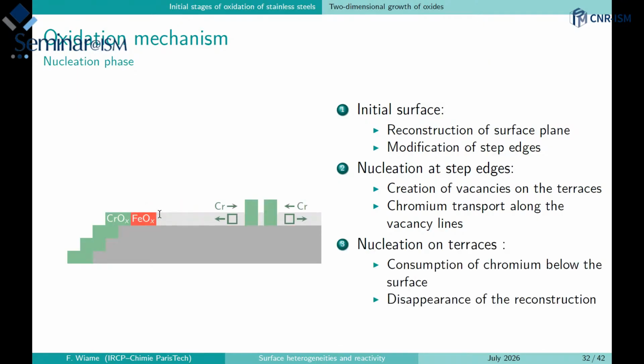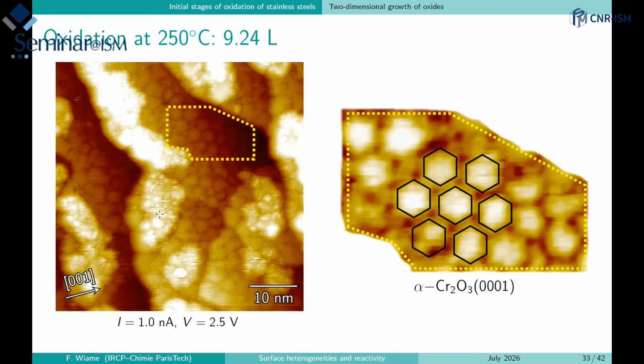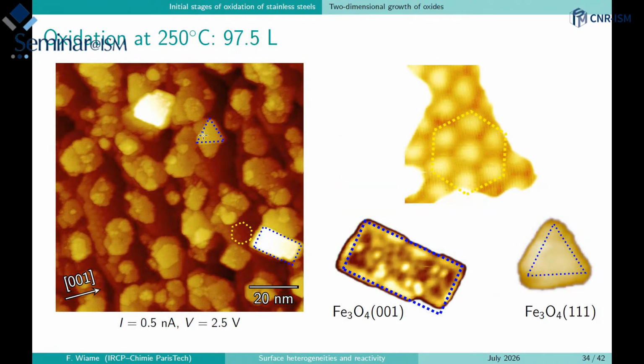And then we have the formation of the nucleation of chromium oxide on the terraces. So that means that we already have consumed all the chromium from the top surface, and also the appearance of some iron oxide. If we continue the exposure, then we have another structure, a hexagonal structure of chromium oxide, which is appearing on the surface, which is now covering the whole surface, but we already have the iron oxide at the step edge, which will continue to grow.